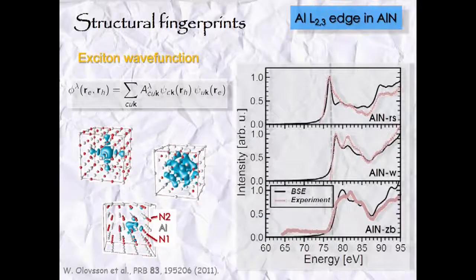Okay, so we make this ansatz basically for the electron hole wave function. Knowing the conduction or the core states and the unoccupied states from the ground state, we combine them into products of these two, and then we use all possible products that we have for our k points as a basis for the two-body equation. For the ground state, we use LAPW as the basis.